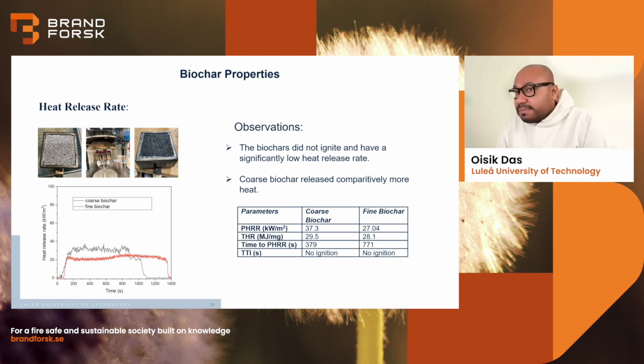We did the similar thing for the biochar in our lab at Luleå University of Technology. And we see that, interestingly, the biochar did not ignite and had a very low heat release rate. However, the coarse biochar has a little more heat release compared to the fine one. But the peak heat release rate, which is the highest point in a heat release rate curve, which we see on the left side, for both the biochars was very low, like 37 and 27 kilowatt per meter square. If you do it for plastic, for example, polypropylene, it's over 1,000 kilowatt per meter square.